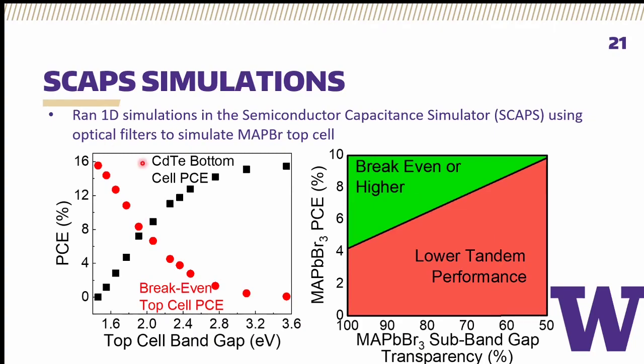So then what we did is we took a 15.5% efficient CdTe device in the semiconductor capacitance simulator, an all-in-one 1D device simulator. The model had been optimized by our collaborators at Colorado State, and we wanted to see exactly how much haze could be tolerated in a perovskite CdTe cell before the CdTe cell would be better off without the perovskite whatsoever and would just be better standing by itself. These are the results that we got. And we have this very aggressive curve that you see right here.